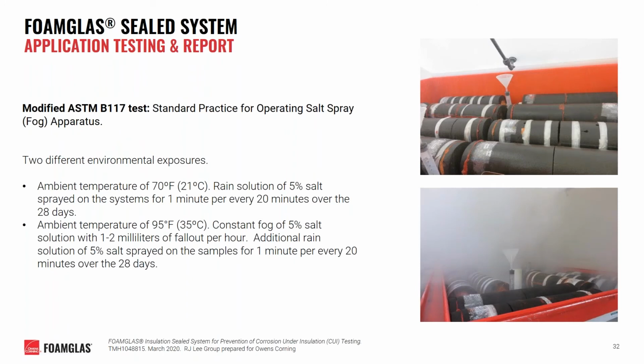During development, we also conducted multiple different tests to document the performance of this system. One of these was a modified ASTM test that tested the system within 2 different controlled environments over 28 days. One chamber was simulated with a salt solution of rain, while the other was simulated with a salt solution of rain and fog. In our experience of running these tests, they are considerably harsh to unprotected metal pipes and often exhibit very obvious signs of corrosion upon conclusion.